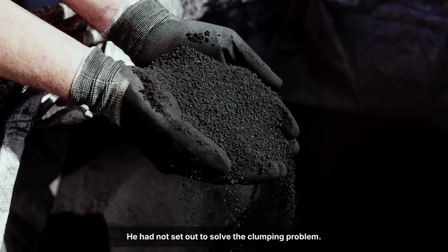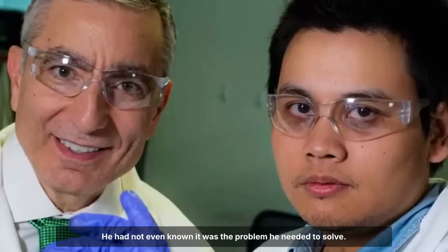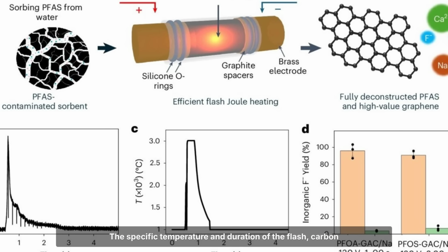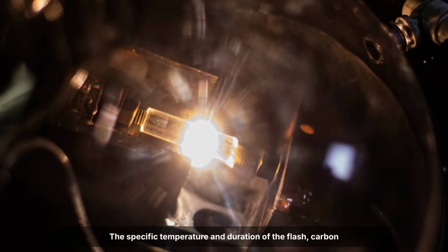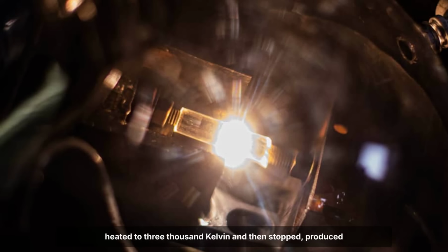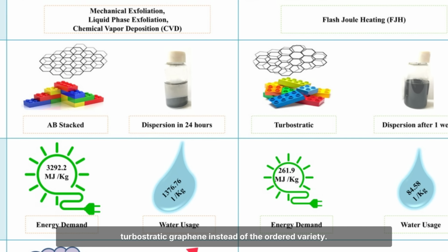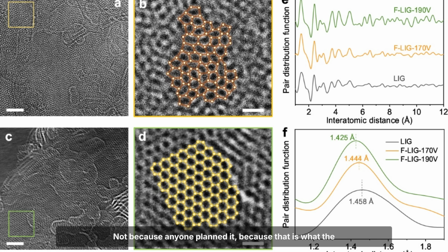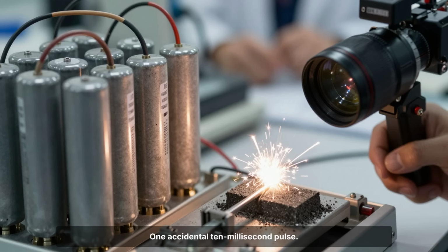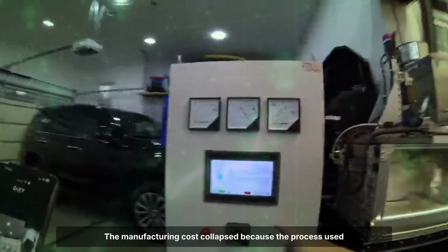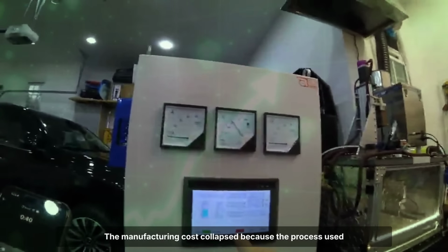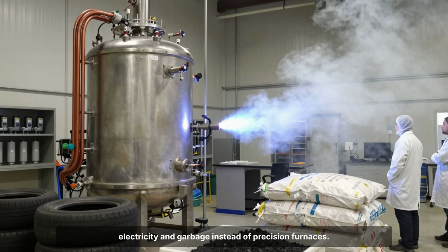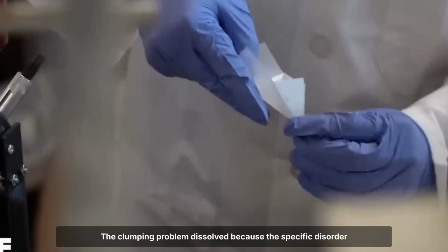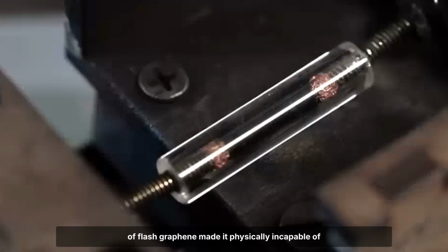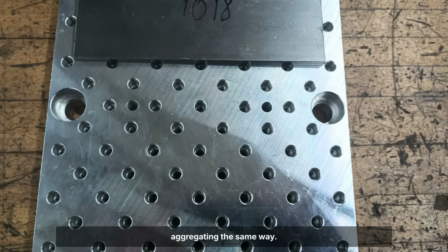Luong had not designed this, he had not set out to solve the clumping problem, he had not even known it was the problem he needed to solve. The specific temperature and duration of the flash, carbon heated to 3000 Kelvin and then stopped, produced turbostratic graphene instead of the ordered variety. Not because anyone planned it, because that is what the physics does at that temperature. One accidental 10 millisecond pulse. The manufacturing cost collapsed because the process used electricity and garbage instead of precision furnaces. The clumping problem dissolved because the specific disorder of flash graphene made it physically incapable of aggregating the same way.